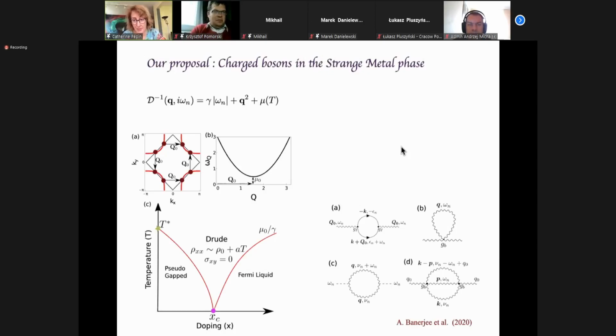So it's something we did with our postdoc. And so the bosons interact with a soup of fermions. So they have 2 types of particles. They are incoherent, so they don't participate to Hall conductivity. So the idea to explain the mystery of the cuprates would be that bosons would kind of short circuit the transport for linear resistivity. And on the other side, you have a fermion soup which could be responsible for sigma xy, with sigma xy over sigma xx having a T squared lifetime.